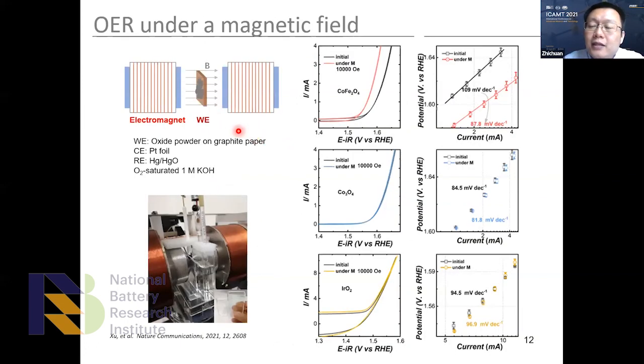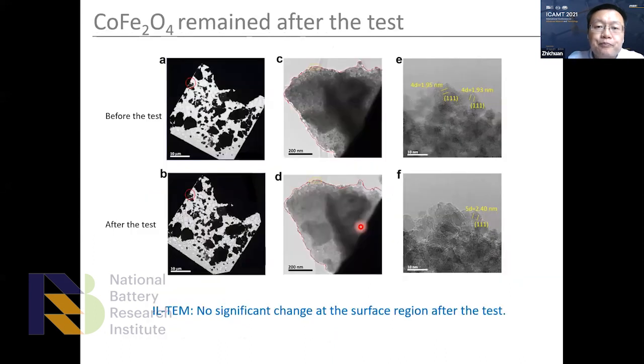And then we tested OER under the magnetic field. Basically, this is the setup here, and this is the CV measurement. You can see the increment after applying the magnetic field: we can observe the increment of OER for the cobalt iron oxide. But for the other two electrodes, there is no increment, all right?